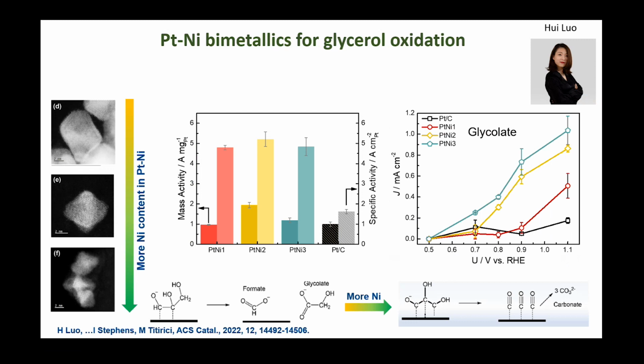So to avoid this poisoning, we thought maybe we could try to add some nickel atoms to platinum. This is Hui Luo, who was also a former postdoc of mine, who started all this research, and who's now a lecturer at the University of Surrey, and we are still collaborating very closely on this topic of biomass oxidation. Basically, she added some nickel to platinum, and I don't want to go through the details, but we compared the pure platinum catalyst, a catalyst where we would have an excess of platinum atoms to nickel, a catalyst where we've managed to have one platinum near one nickel atom, and another catalyst where we had an excess of nickel.